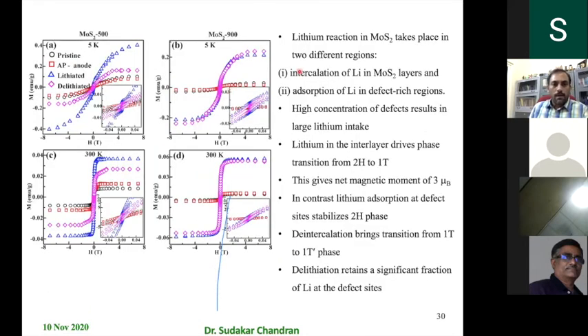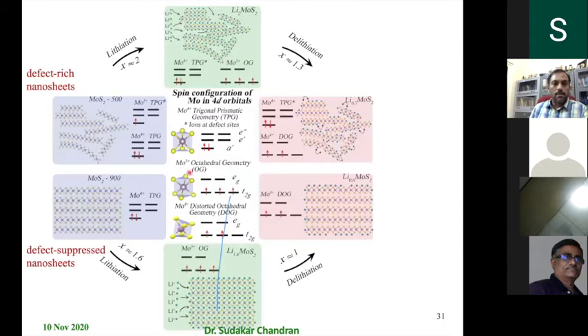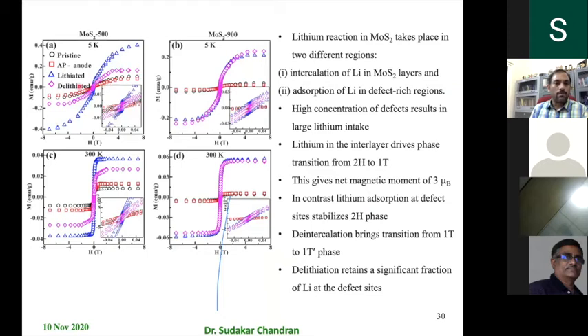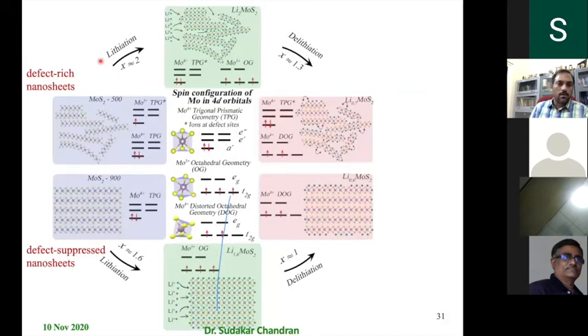So the large amount of lithium is retained in the defect-rich nanosheet, whereas the retained lithium is less in this case. So in moly disulfide, which is kind of defect suppressed, when the lithium is extracted, it doesn't change much, as you can see. So there is a lot of interesting things happening, and that can be understood from this particular picture. You have a defect-rich moly disulfide to begin with, in which the moly is in 4+ and 5+ states. The moly in the defect sites is mostly in the 5+ state, which will have an unpaired electron. And this unpaired electron is what explains the magnetic properties of the pristine MoS2 in the defect-rich case, like the bound magnetic polaron model I explained.